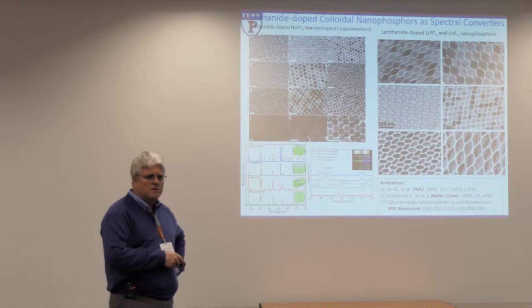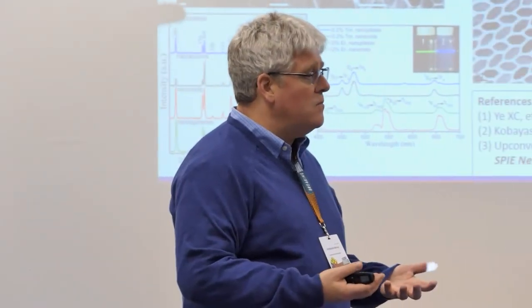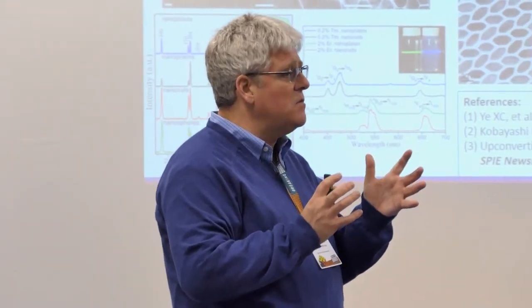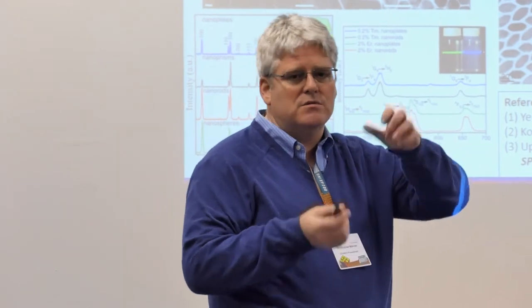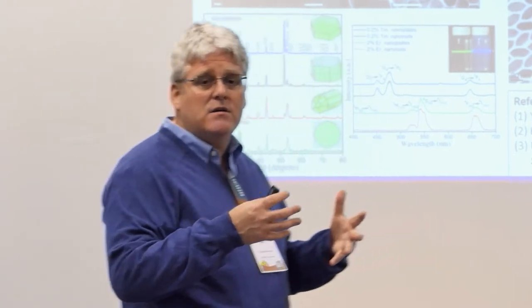And so now we're starting to have things that have directionality in their interaction. And in keeping with my analogy of trying to turn this into chemistry in the sense of using our artificial atoms, this is hybridization. So we think about shape as being the surrogate for valency when we think about hybridization of atoms, whether something wants to have four nearest neighbors or six nearest neighbors. Symmetries that are accessible are now going to be dictated by the geometry in packing rather than the molecular orbitals or electronic orbitals of the individual atoms.